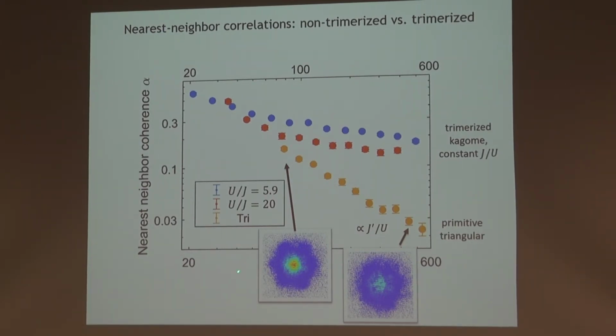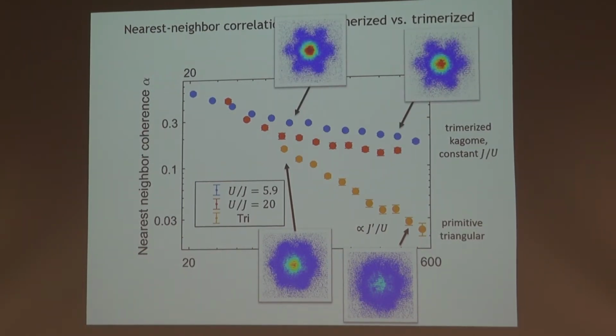The images here still show some sort of 6-fold modulation, which is the signature of coherence, but by the time we get to this point, even that little bit of coherence is extinguished. In contrast, in the trimerized Kagome lattice, even when we're deep within the Mott insulating regime, even long after long-range coherence has been totally killed in the system, we still see a great deal of nearest neighbor coherence in the system, which we expect because we've retained these strong bonds.